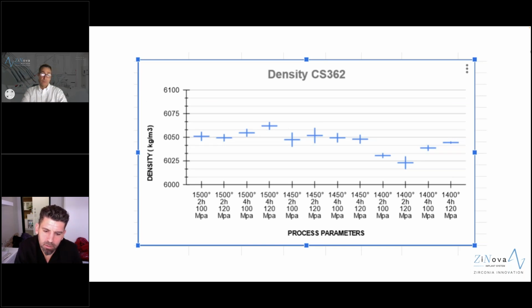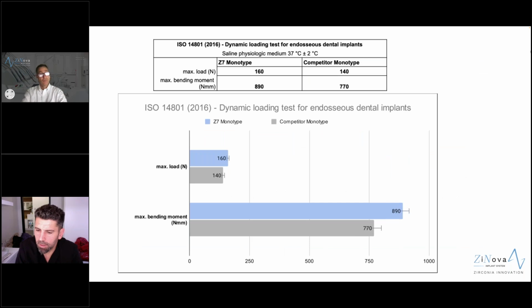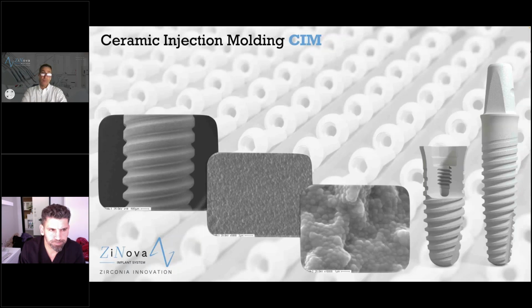The density, again, not only the grain size, but the density of the material will change depending on the different parameters, as we said. And again, each company has their own method. Our particular company, our internal studies showed that in the dynamic loading test, ours was higher than the competitor monotype. So this is for the one-piece implant. Our proprietary method showed higher bending moment and maximum load compared to one of the competitors.